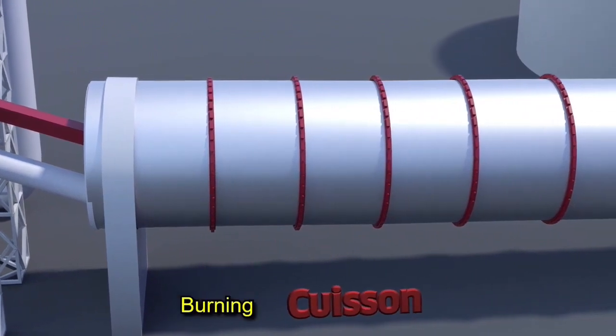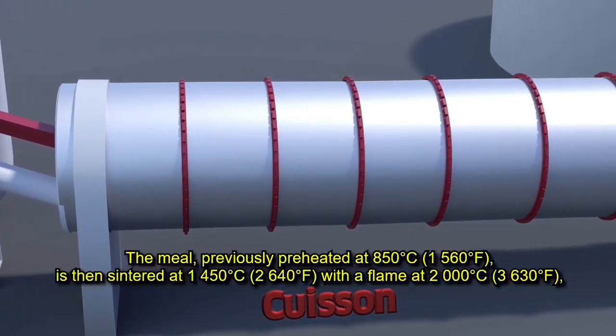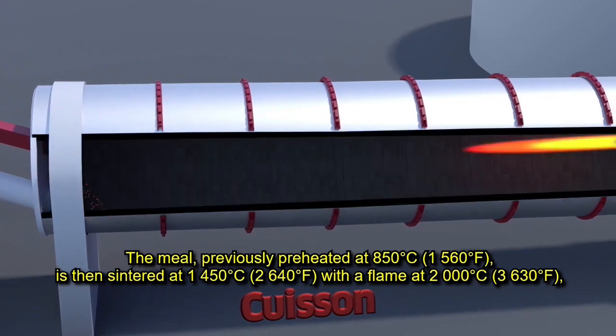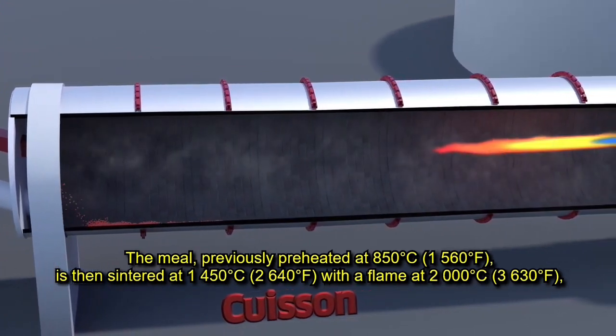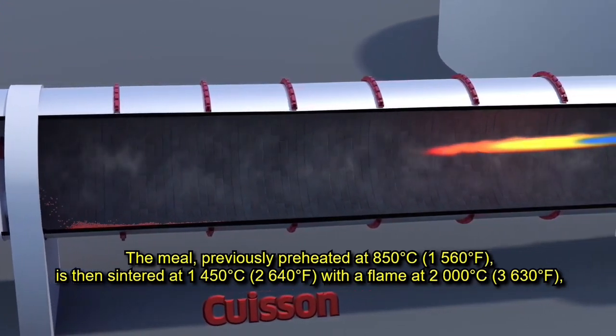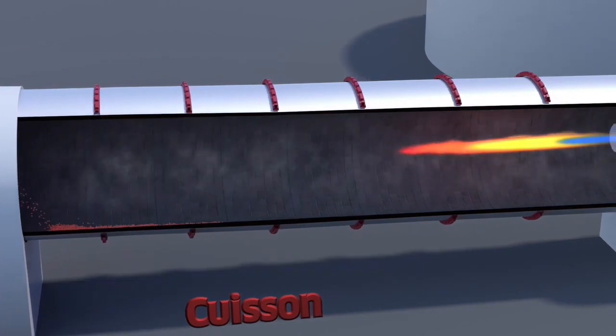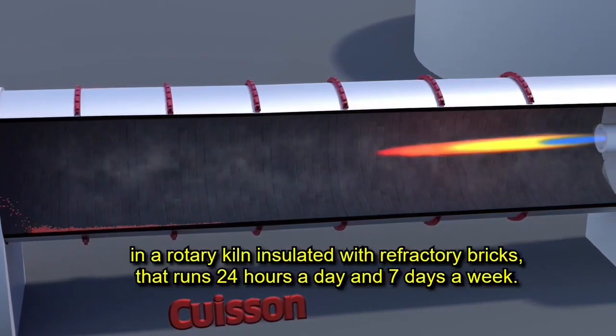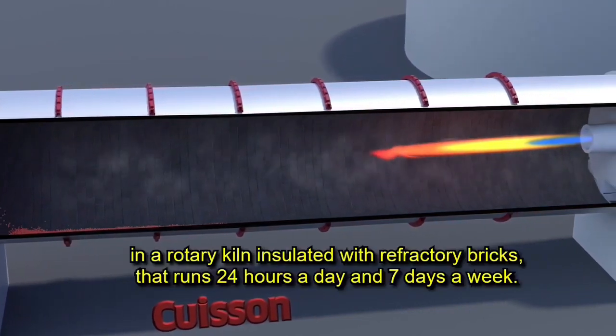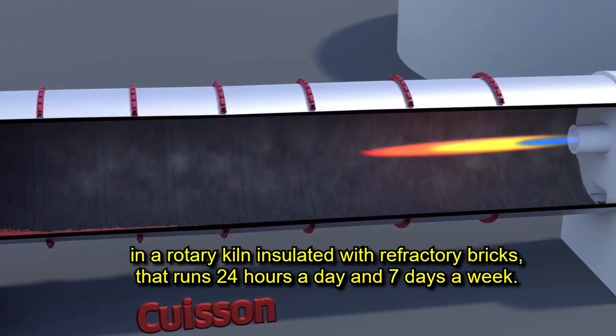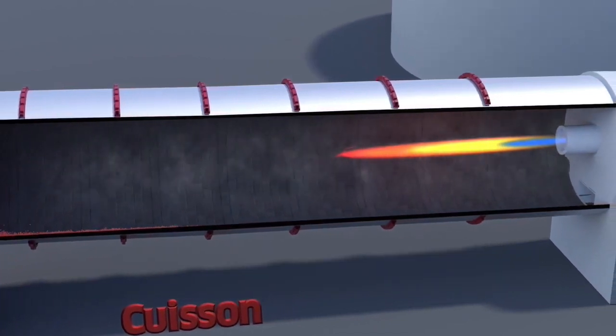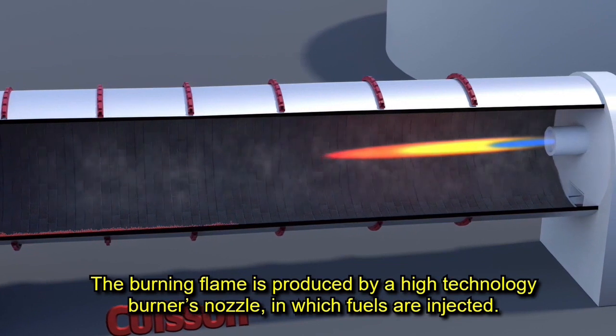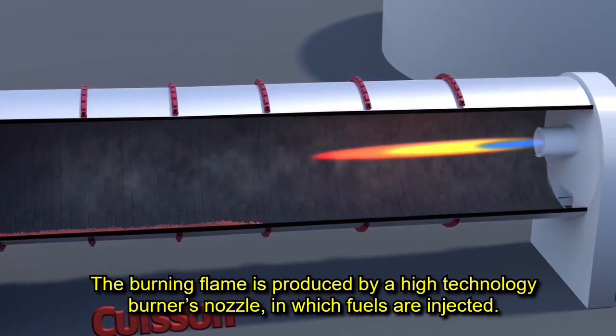Burning. The meal, previously preheated at 850 degrees Celsius, is then sintered at 1450 degrees Celsius with a flame at 2000 degrees Celsius in a rotary kiln insulated with refractory bricks that runs 24 hours a day and 7 days a week. The burning flame is produced by a high-technology burner nozzle in which fuels are injected.